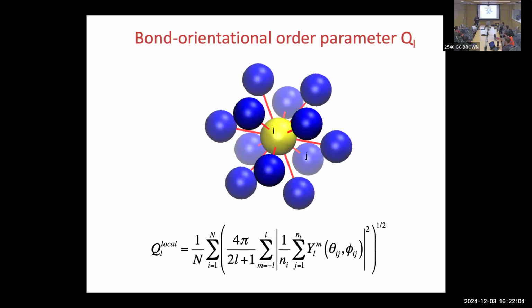So is that capital Y your weight? This is actually the Y_lm's from quantum mechanics. And so these l, m are basically, let's see, I'm looking at Q6. The Y_lm's will be the largest if the i and j's, so the i is the central particle, the j are the neighbors, are in the right positions, given by the theta_ij, which are the spherical coordinates. Then this Y_lm will be largest.